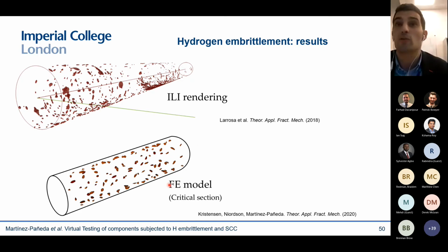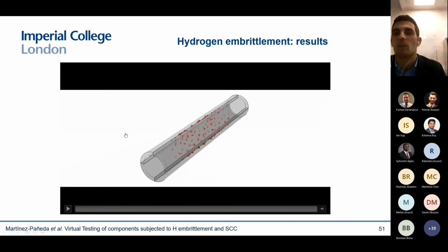We can very easily introduce those defects into our model, because in these phase field models you solve for the phase field as a degree of freedom. So you don't need to create a new mesh for every different pit distribution that you find. You have the same model for all pipelines, so that can save you a lot of engineering time. Depending on the location of the pits, you just decide which ones will start with a phase field equal to 1. Basically, we can then model those pipelines under in-service conditions, and this is what you see in this video.